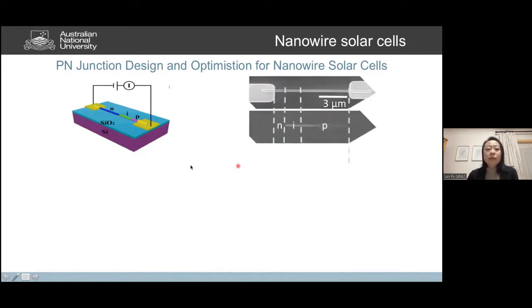By developing this electron beam induced current technique, we can image in the SEM system the electron beam induced current that's generated from the PN junction. So by doing that, you can see that if we've grown the PN structure in the nanowire, and this is the SEM image, when we do this EBIC, you can see very nicely that the EBIC current correlates to the built-in electric field inside the nanowire.